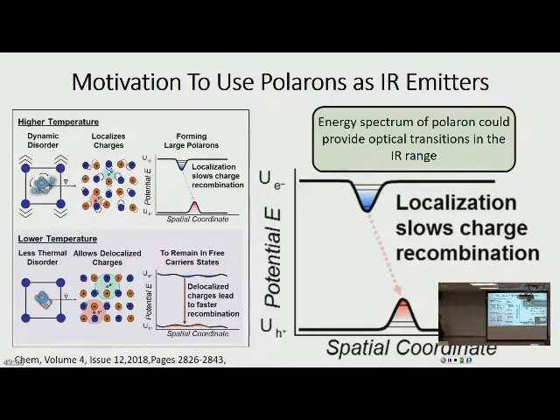So these wells, the deeper they are, the bigger coupling you have between the charge and certain phonon modes. So this all depends on the type of atoms you have in the lattice. Right, it's very material dependent. Not so much nanoparticle size, as long as it's big enough, as long as it's bigger than the polaron that forms. Otherwise you get a quantized polaron, and I'm not sure what the physics would be behind that.